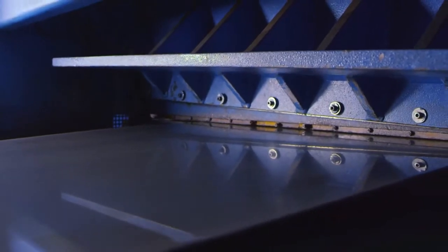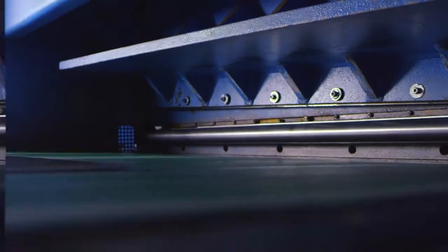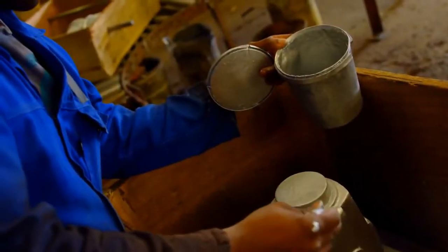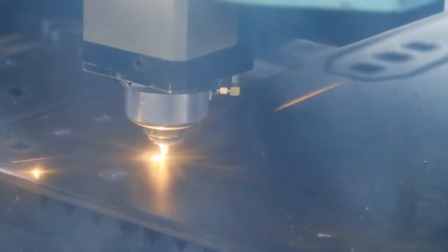Finishing. Now, using a mechanical trim press, cut each of the raw castings into approximate dimensions. A scrap metal shredder is used to recycle the scrap aluminium, which is then reused in the oven. The primary casting is then X-rayed to see whether it has any internal flaws. For fittings, the validated casting is further improved with a laser trim and drilled on a CNC machine.